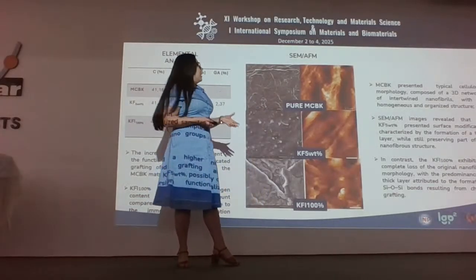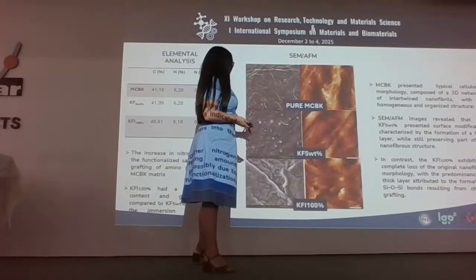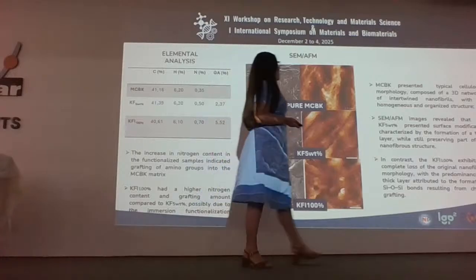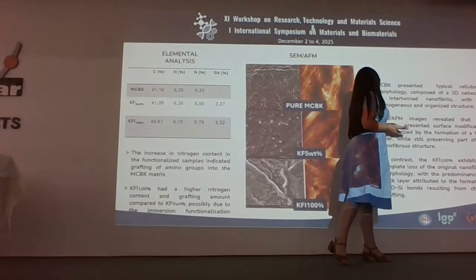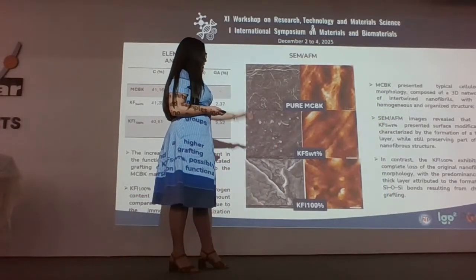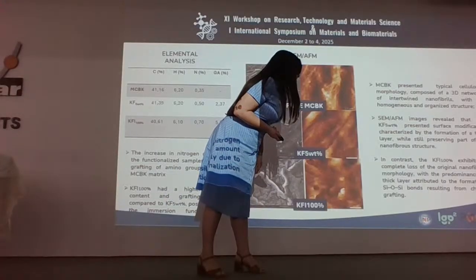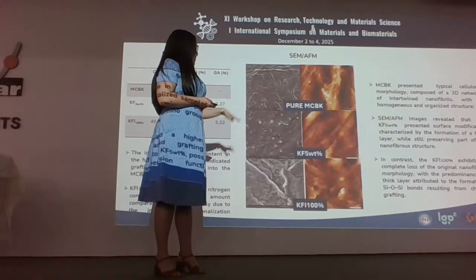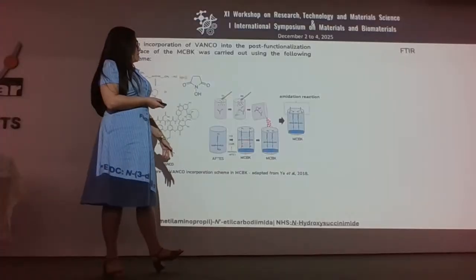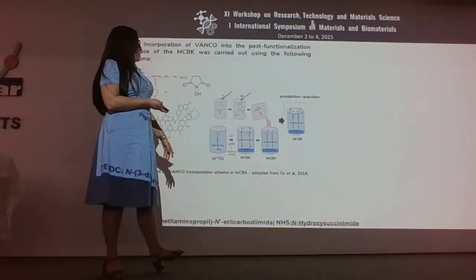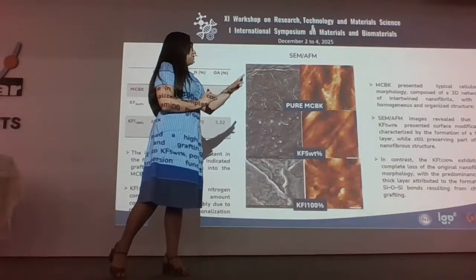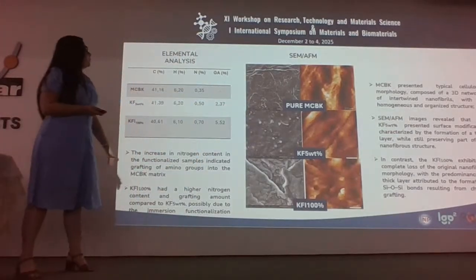In the first morphological image, it is possible to observe the typical conservation of nanofibrils of the bacterial cellulose, and in the second condition it is possible to see the formation of a thicker layer, and in the last condition it is possible to observe the predominance of the structure of the nanofibers. It is possible because the last condition is the greatest success of the chemical functionalization.